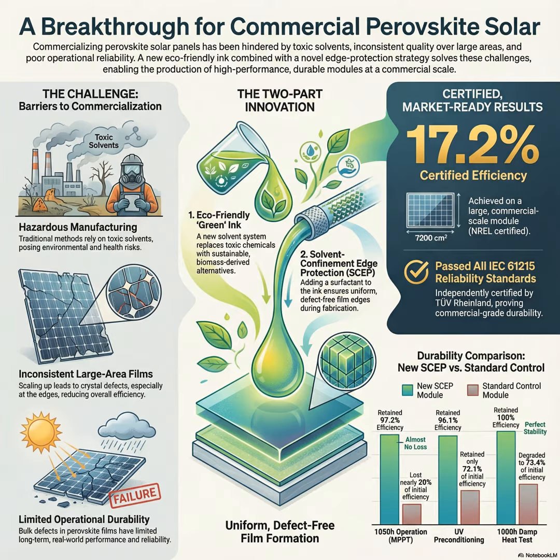And what about just running them day after day, continuous operation? That's the operational stability test. They ran them under continuous maximum power point tracking, which simulates the module constantly optimizing its output under the sun. After 1,050 hours, they still had 97.2% of their initial efficiency. Again, the control group lost nearly 20% in the same test. So it proved the panels are stable while they're actually generating power.